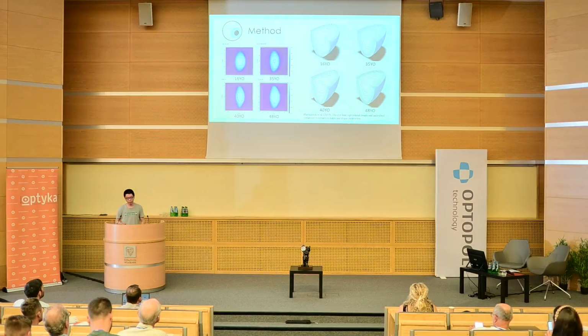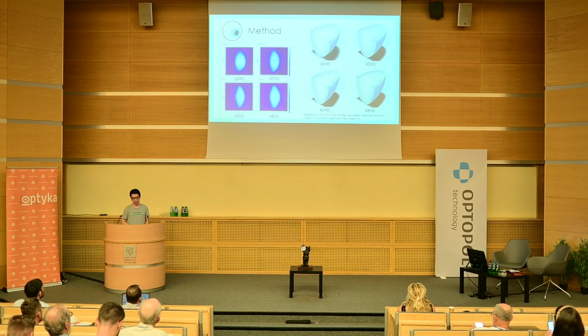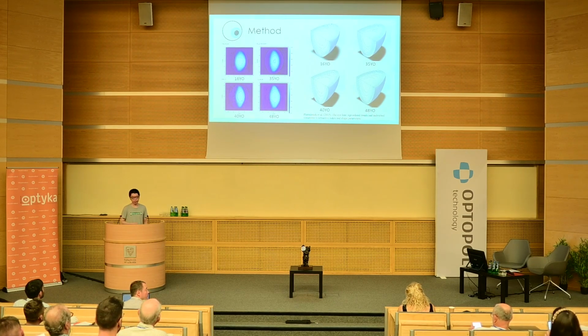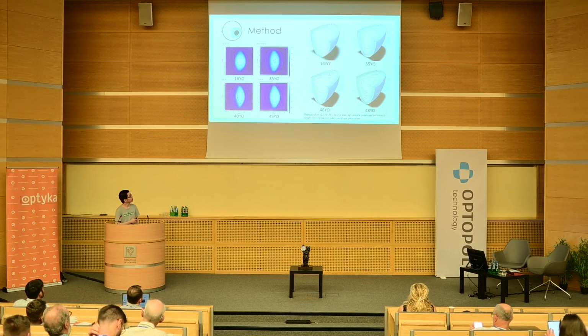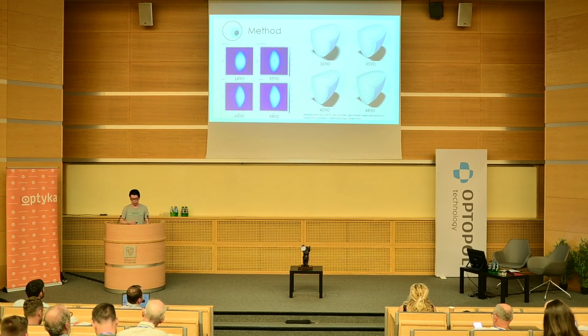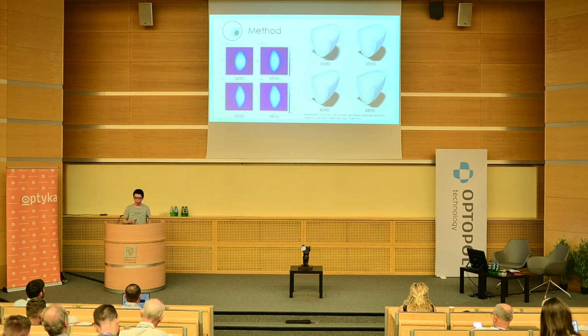Our model profiles were derived from the refractive index contour of the human eye lens. We used the spline curve to fit the refractive index profiles in SolidWorks and built a quarter model of each lens. The cortex of the lens was divided into many layers, and each layer was assigned different material properties.